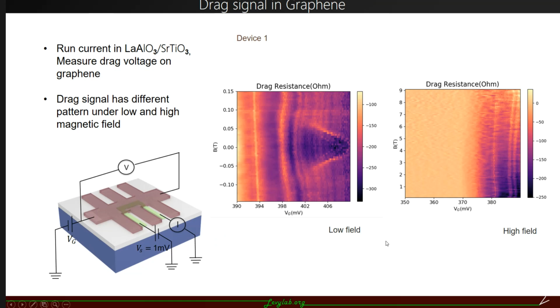Here we swap the drive and drag layers to measure the drag voltage in graphene. So we're running the current in the LAO/STO and then applying a gate to the graphene at the same time to make sure the LAO/STO is conducting. And we measure the drag voltage in the graphene. This drag voltage shows different features at low and high magnetic field.